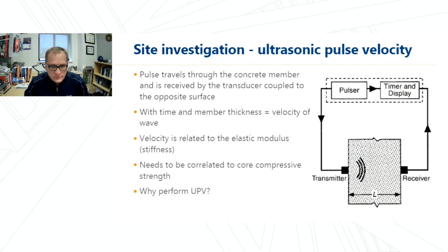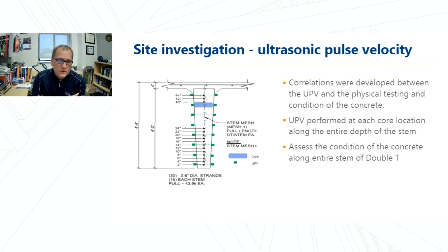So why did we perform UPV? Because with the continued reaction of DEF, the stiffness of the concrete will decrease. So we were trying to pick up differences in the stiffness of the concrete associated with the DEF. So we did this by taking our UPV and measuring the pulse velocity at different elevations from the bottom of the stem. And we also, at specific locations, extracted cores through the entire stem at the locations where we had previously measured the UPV. Again, we were trying to establish the correlation between the velocity and the strength of the concrete. And we did this on numerous double T's to have a pretty good understanding of the velocity and the strength of concrete.